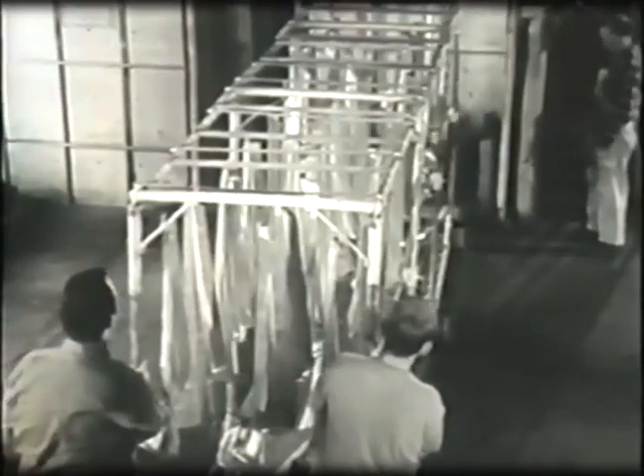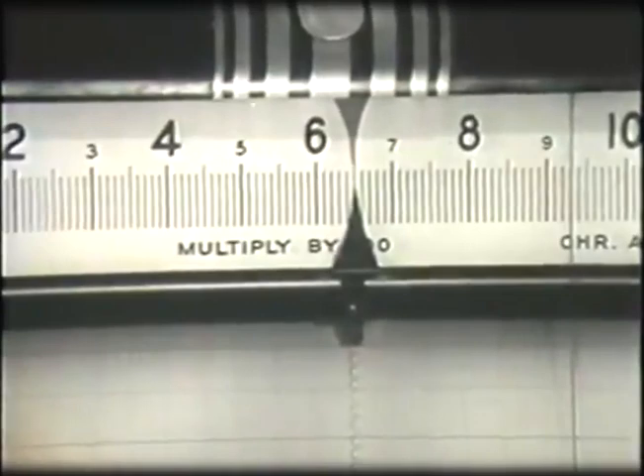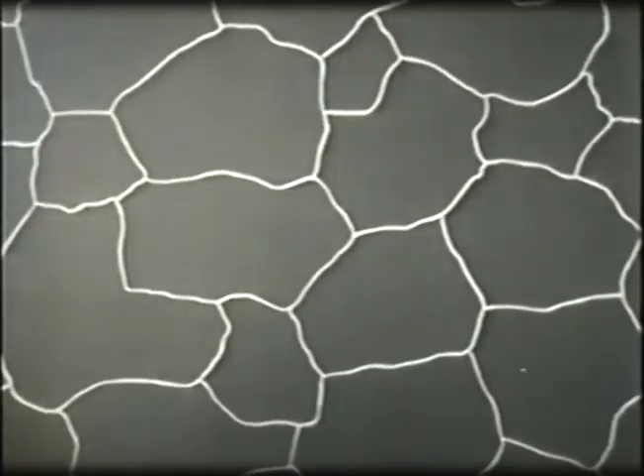In order to remove the effects of cold working and to soften the alloy for further forming operations, the strain-hardened alloy is annealed in an air furnace. Annealing is done at approximately 650 degrees Fahrenheit, and its effects are almost instantaneous. Annealing first relieves the internal stresses caused by cold working. As the metal is heated to recrystallization temperature and above, the nuclei of new grains are formed from the fragments and crushed particles of the original grain. These nuclei may merge with other fractured particles or with portions of the original grains growing into new stress-free grains. The metal is now annealed and in a soft condition for further forming.